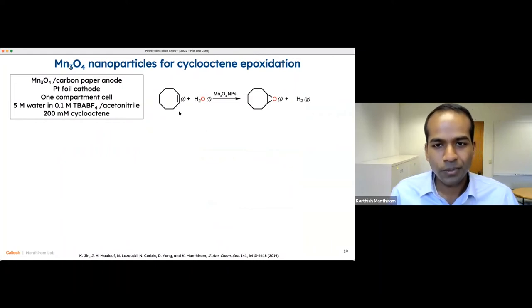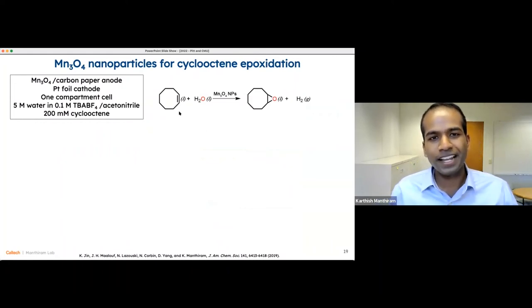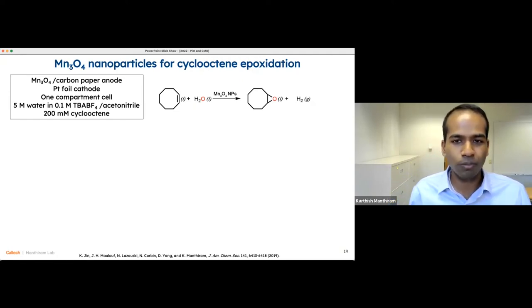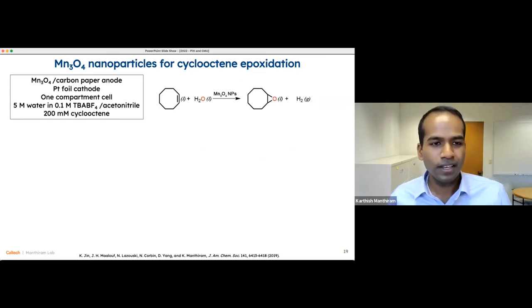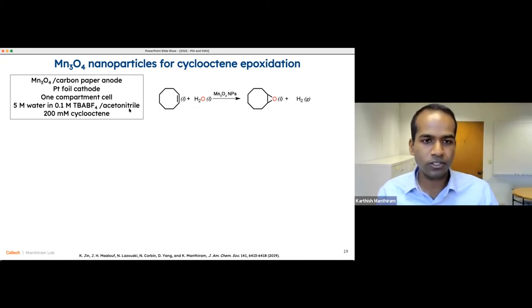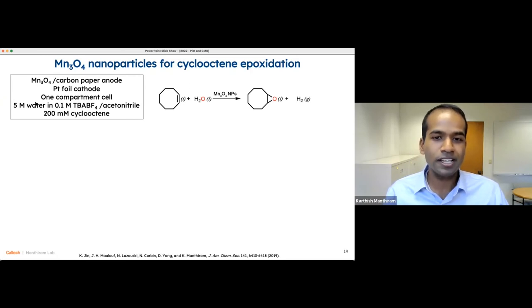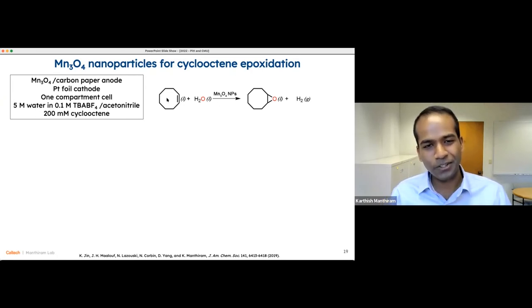So here, first, we are looking at a model reaction, that of cyclooctene, and that is a nice substrate to use because there are a lot of literature reports that we can compare to. We're using platinum foil as the cathode, so there we haven't really invested significant efforts in finding cheaper or alternative catalysts. We're doing this in a one-compartment cell. The electrolyte is 5 molar water with 0.1 molar TBABF4 in acetonitrile, so we need a mixed electrolyte since the water is the O atom source, but if we were to use water alone, the cyclooctene wouldn't be soluble, so you need a mixed electrolyte with acetonitrile and water.